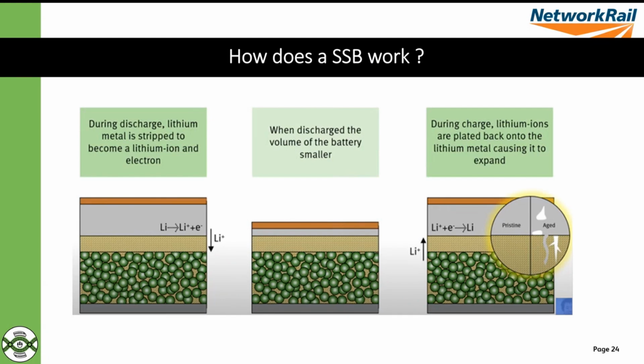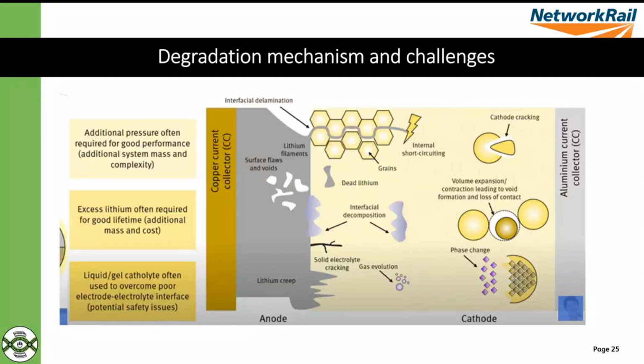How does it work? Well, during discharge, lithium metal is stripped to become a lithium ion and an electron. When it discharges, the volume of the battery reduces, and then during charge, the lithium ions are plated back onto the lithium metal, causing it to expand. So this constant expansion and contraction can be problematic, and this stripping and then depositing back on can be problematic as well. I've just shown this as an example of some of the challenges we get with solid-state technology.